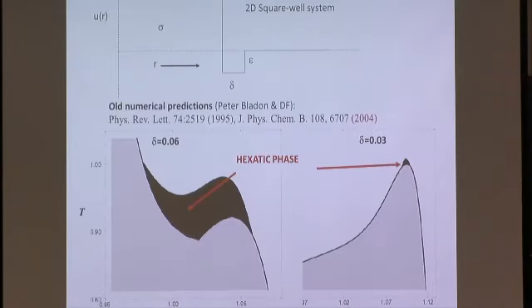Now, we actually then did simulations and showed that depending on, we did a very simple model potential, hardcore repulsion, short range attraction, this is the range of the attraction, and then depending on the range of attraction, you can get either a very narrow hexatic bulge on a two-phase, so this is a solid-solid transition, density, critical point, and here the hexatic range, the black. Here you have a much larger hexatic range, solid, and here actually solid liquid. And we did this in 1995, and then actually a second paper in 2004.